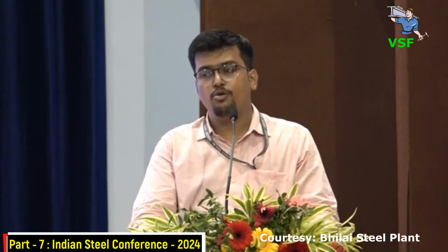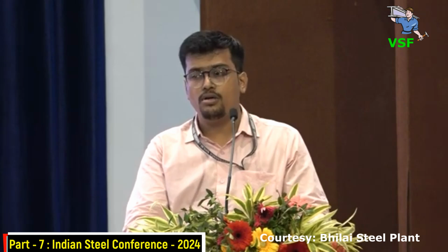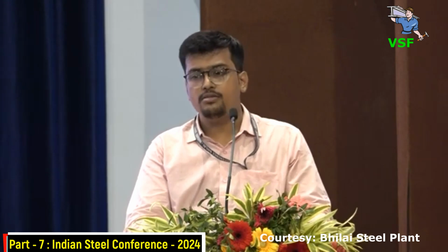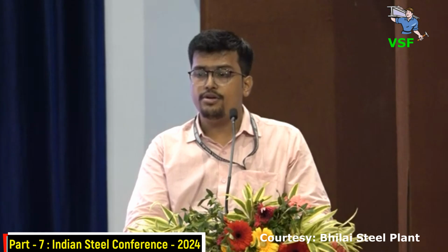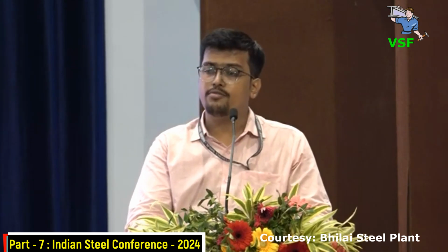Concluding our trials, the main objective of our trial was reduction in coke moisture so as to reduce the coke rate. With addition of surfactant, coke moisture of block 2 coke reduced from an average of 5.1% to 3.1%. This was on 1 week trial, so the data was based on that. Coke rate of BF4 BSL also reduced from an average of 445 kg per ton of hot metal to 442 kg per ton of hot metal.